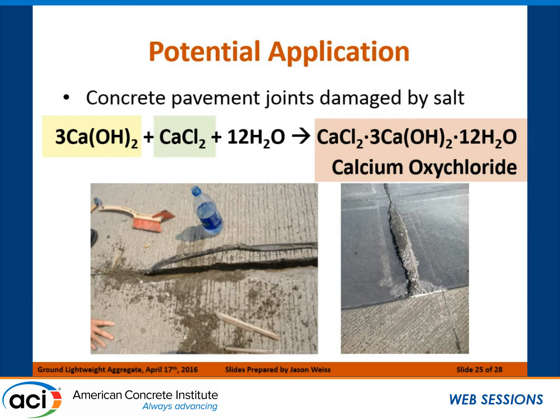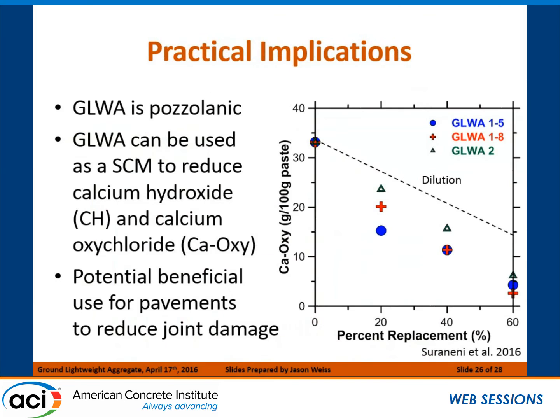And the reason is it breaks up concrete, especially where you have high salt concentrations. This undergoes a fairly high volume change and can cause pavement joints to start looking like this after only a short period of time. The good news is there's three really simple and easy solutions to this. One is to use topical treatments like sealers. One is to carbonate the surface of your concrete. And the third one is to really start looking at the improved use of pozzolanic materials. So here what we're plotting is the amount of calcium oxychloride that's being produced versus the percent of cement that's being replaced with a pozzolanic material.